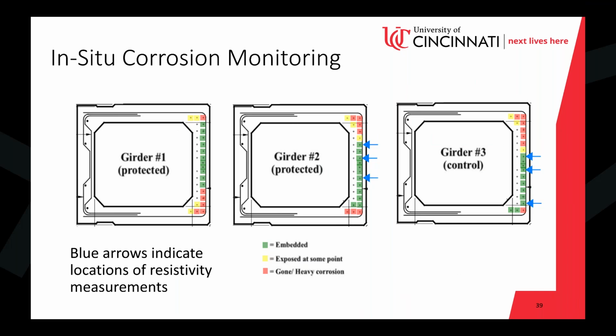So we're putting connections on both sides of them where the metal is free. A lot of prep work to do that. But we chose in each of these fully embedded strands. So these are strands that have not had the concrete spall off next to them. But we intentionally chose some that were both completely embedded and away from where the damage on that box beam was, versus some that were very close to their neighboring strands and were partially exposed at some point. Hoping that we would be able to capture one of these things actually corroding in situ. We also chose, of course, 3 on one of the cathodically protected versus 3 on the control.